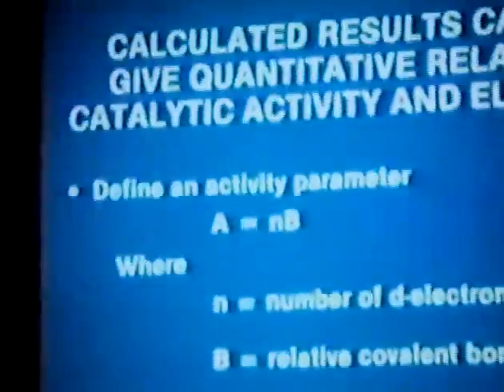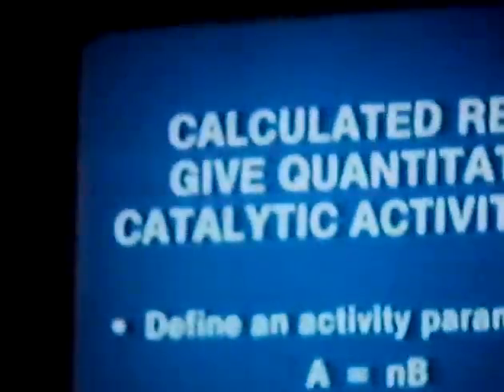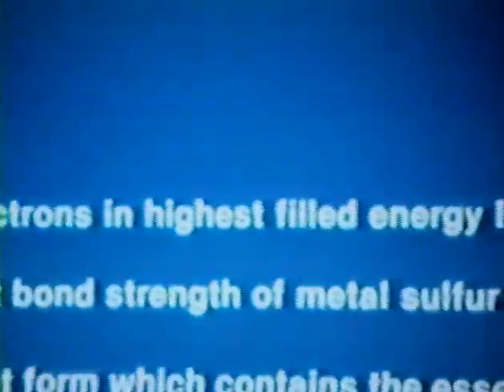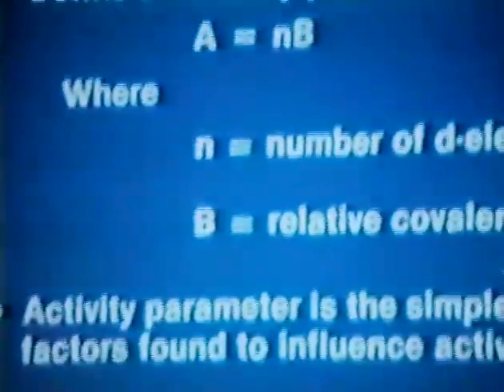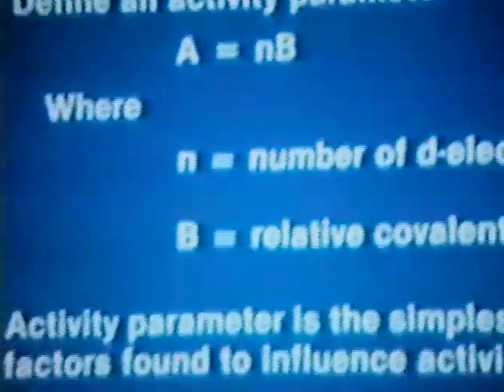Those factors are shown in this slide, and I am going through this very rapidly in the sense that I've left a lot of details out, which is in the paper and literature. But basically, when you look at these trends, you find two things: that the number of d electrons in the highest filled energy level are very important to determining which catalysts are most active, and secondly, that the relative covalent bond strength of the metal-sulfur bond is also a factor which is important. You get this by doing your sums and differences in the antibonding and bonding orbitals, as anybody doing this would recognize.